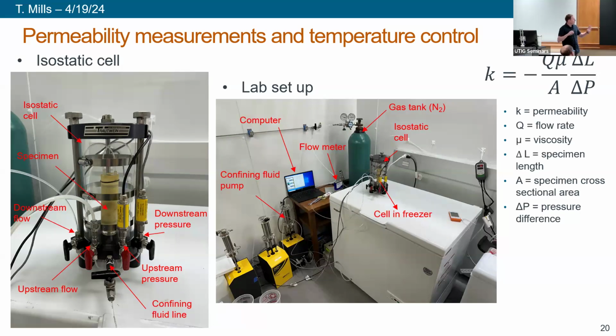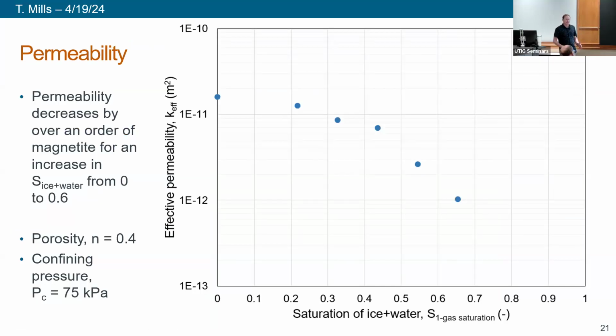And so after this painstaking effort, we finally have some data that we're happy with and we think is representative of what's happening in our samples. And so this plot is showing effective permeability on the y-axis on a log scale and the saturation of ice, and then a tiny bit of liquid water on the x-axis. And so essentially this is the saturation of 1 minus the gas saturation.